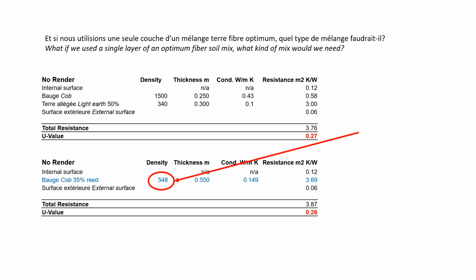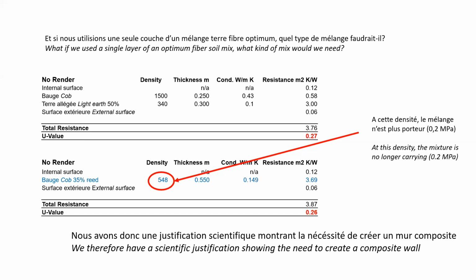So if we decided to use only one mix and use this hypothesis, a mix that would be optimum would have the same thickness of what we tried out previously. So here we've got a 55 centimeter wall. To get a U-value equivalent to the one we had previously, 0.26, we would need a cob mix that would have a density of 548 kilograms per cubic meter. And this means that we would have a compressive strength of 0.2 megapascals, and therefore it would not be strong enough and would not be a load-bearing mix.